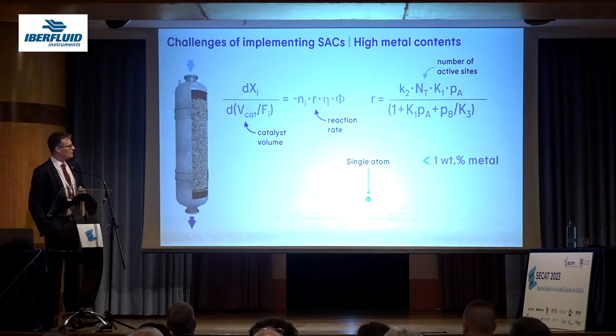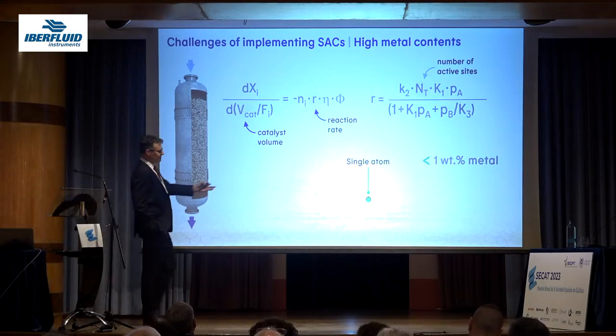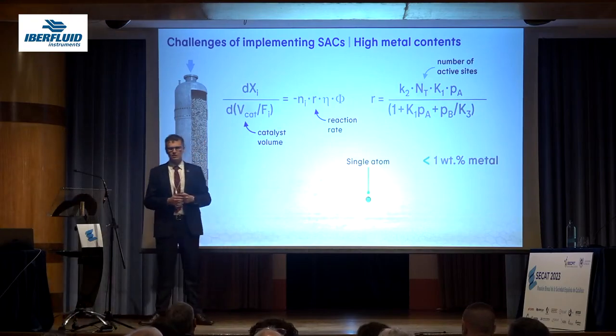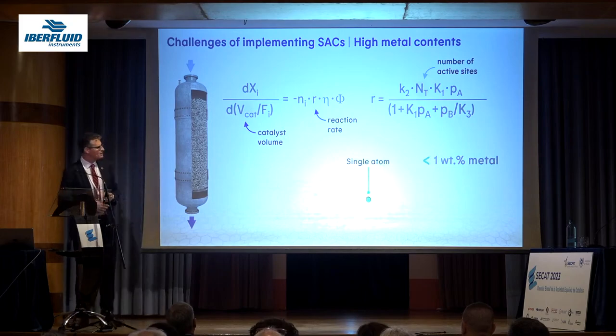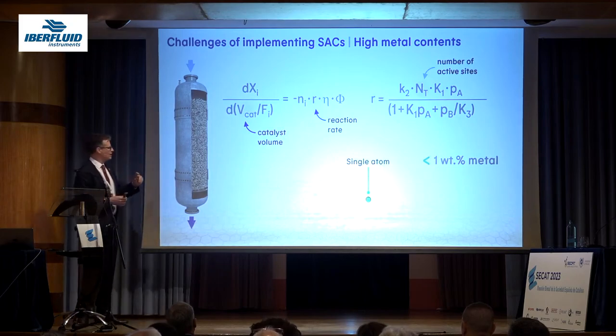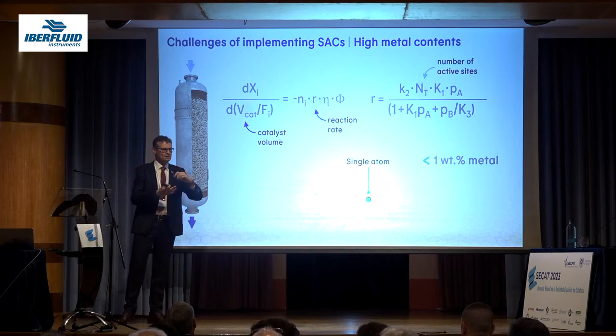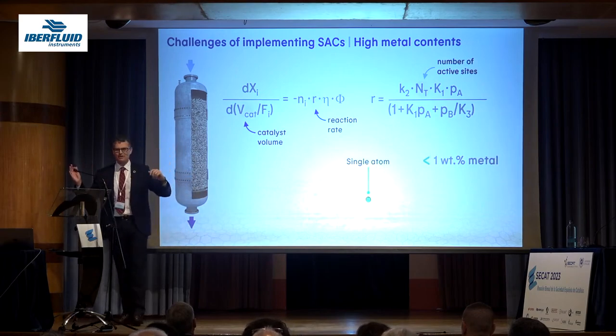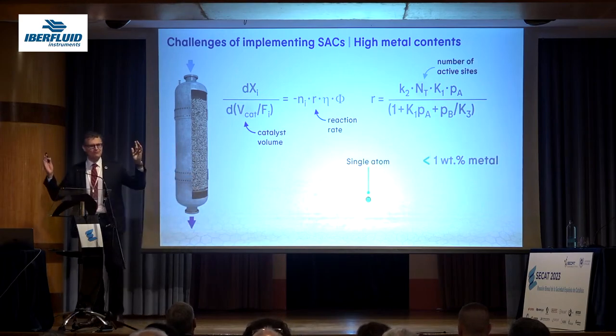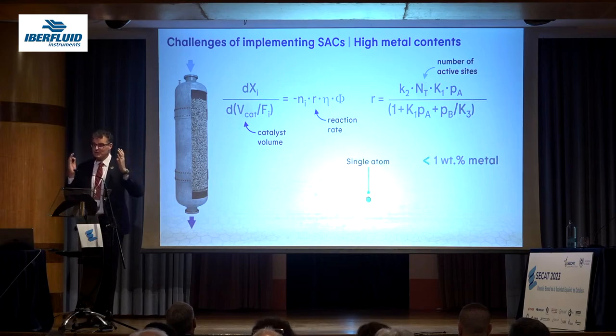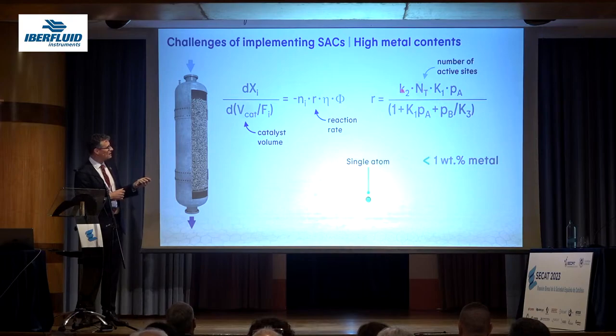Because if the loadings are low, it's relatively easy to stabilize single atoms in this solid host. But you know, what happens is that when you want to make a reactor, you will like to compact activity as much as possible. Otherwise, you have an infinite volume of a reactor, so we like to increase the loading, because if you increase the loading, you increase the number of active sites in the kinetic equation, and if you increase the rate by increasing the number of active sites, you decrease the volume of catalyst that you need in the reactor. This is a very simple notion.